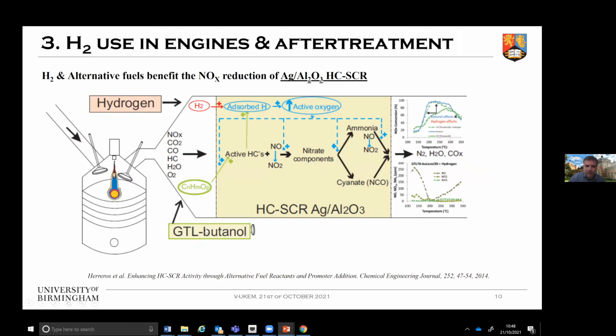And then we observed that by injecting butanol and hydrogen, we were able to obtain very high, close to 90% conversion efficiency in a relatively wide temperature range. What this means is that the fuel, or a very active fuel, can help the hydrogen and make our hydrocarbon SCR system more efficient. So the fuel is also playing a role here.